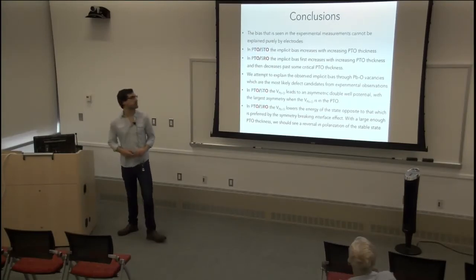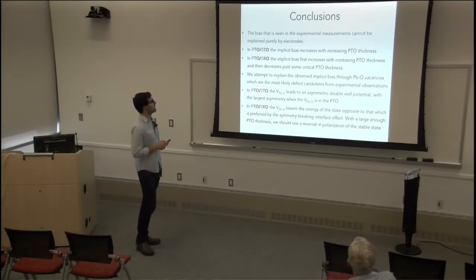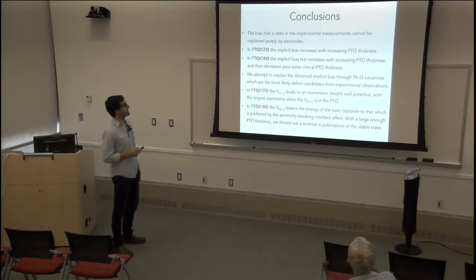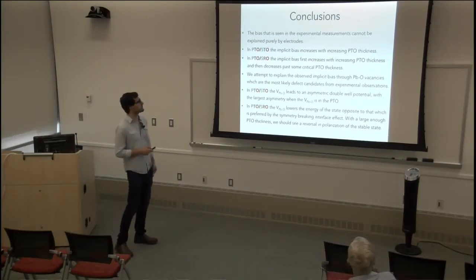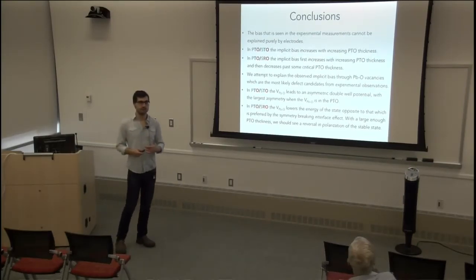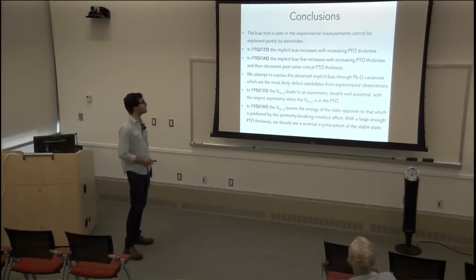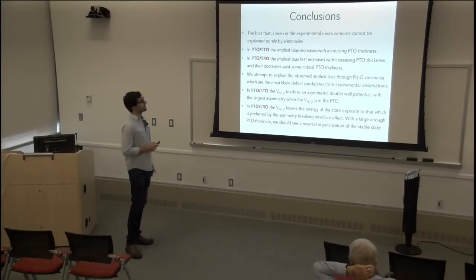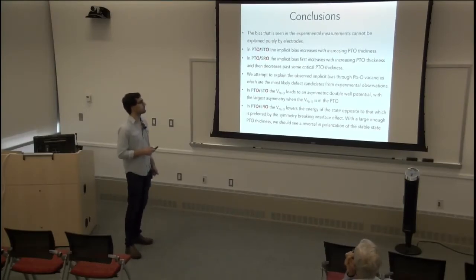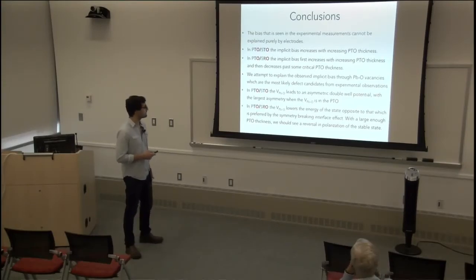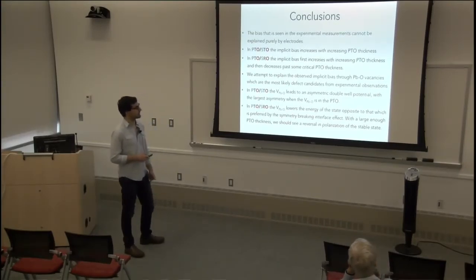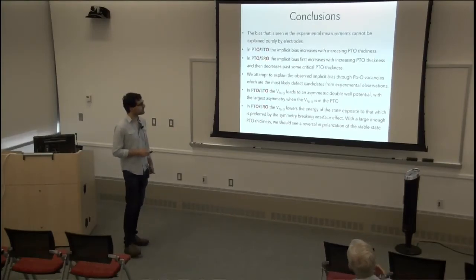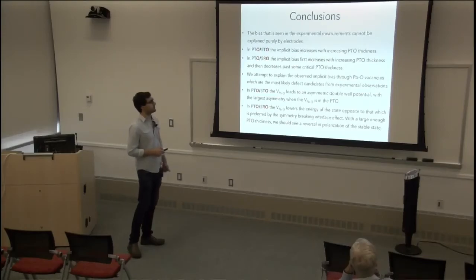Okay. And these are my conclusions that I mentioned throughout the talk: this bias cannot be purely explained by electrodes, because once you have symmetric electrodes, you still have this bias present, while significantly decreased. In lead titanate, strontium titanate, the implicit bias increases with thickness, and in strontium ruthenate, lead titanate, strontium ruthenate, the implicit bias first increases with lead titanate thickness, but then decreases with lead titanate layer thickness past some critical point. And we explain these implicit biases through lead-oxygen divacancies, and we believe they're the most likely candidate